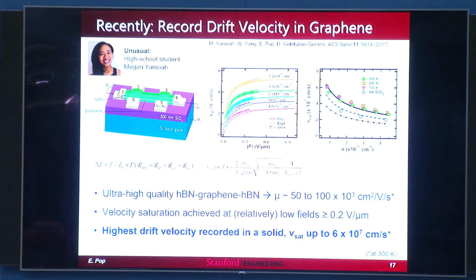Very, very difficult. I do want to highlight that ultimately this is an expected result. We got very large saturation velocities. I think it's the largest one recorded in a solid at room temperature, about 6 times 10 to the 7 centimeters per second. And the numbers are about 50% greater than what we were getting 10 years ago in SiO2. And this is the difference between the remote phonon scattering with SiO2 versus the boron nitride. So that was probably expected. It's nice to know the numbers, but it was probably expected.